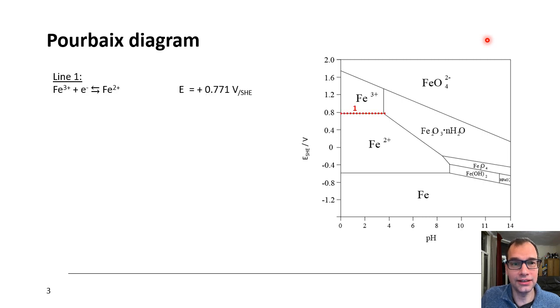Let's look at certain lines. For example, this line between iron 3 and iron 2. This line, you can see here, basically corresponds to this equation. Iron 3 plus electron gives iron 2, and that has a potential which we can just look up. Standard electrode potential of 0.771 volts versus a standard hydrogen electrode. And that's exactly this potential. You see, it's a straight line. It's independent of pH, which makes sense because there are no protons or hydroxides in this equation. So it makes sense that it's independent of pH.